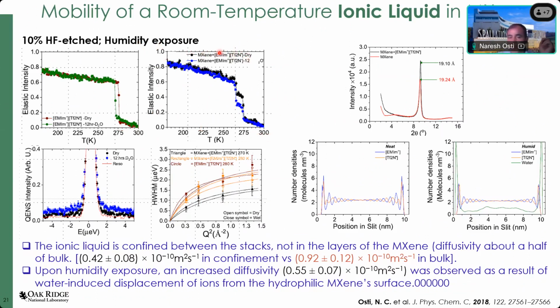Now, this here is the elastic intensity as a function of temperature for the MXene together with the ionic liquid. As you can see, compared to the bulk case, instead of a single step, you see two steps in the elastic intensity decrease, the first step and the second step. This first step is quite similar to the step that you see here, which is coming from the bulk liquid. But this second step is coming from some of the ionic liquid that got intercalated in the MXene.